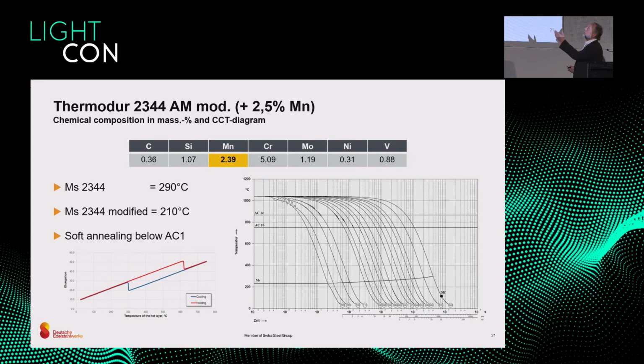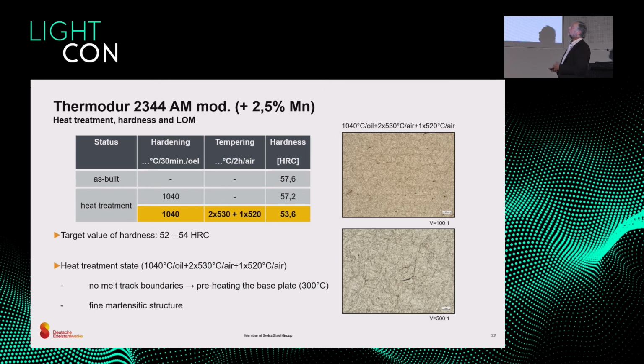It's a view into the future. We changed the standard grade 2344. It's not very easy to manufacture in additive manufacturing. You have to have very high preheating temperatures, and we try to decrease the martensite start temperature without losing the other properties you need for this steel, which the end user knows. Also, in the CCT diagram, very simple. You just have an austenite regime and you have only martensite, so you have to adapt the heat treatment. Very similar properties. It is processable at a temperature of less than 300 degrees, but we did not reach our aim of less than 200, so we still have to work on this grade, so it's not finished.